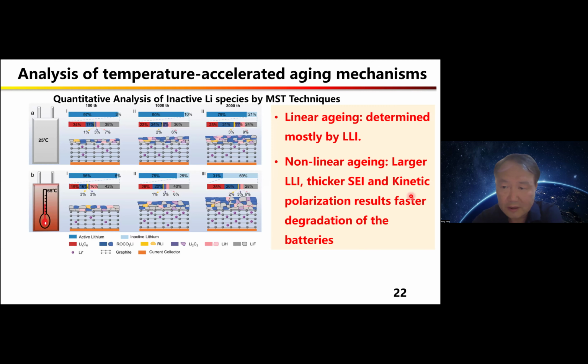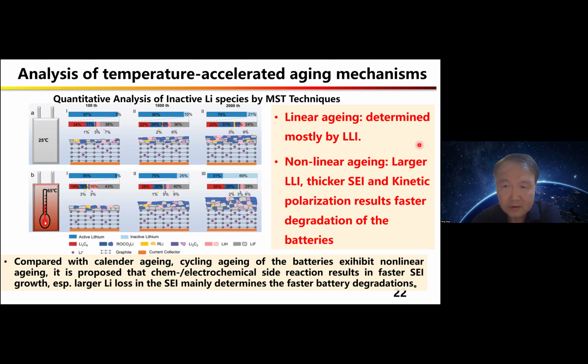So we believe that the linear aging is determined mostly by the loss of lithium, but for the nonlinear aging, larger lithium loss or thicker SEI, even some kinetic polarization, could result in faster degradation of the battery. That is the side reaction at high temperature causing faster degradation of the batteries.